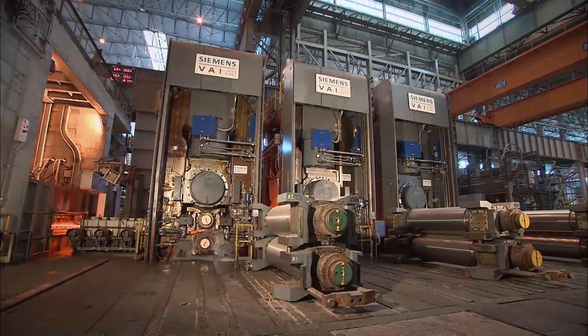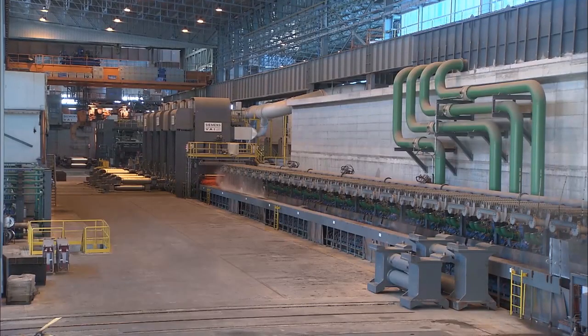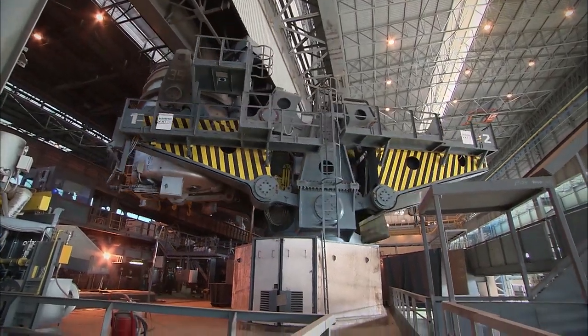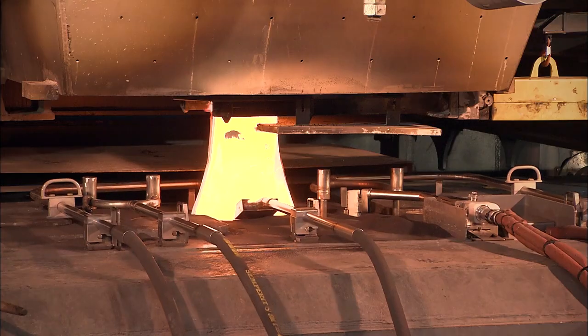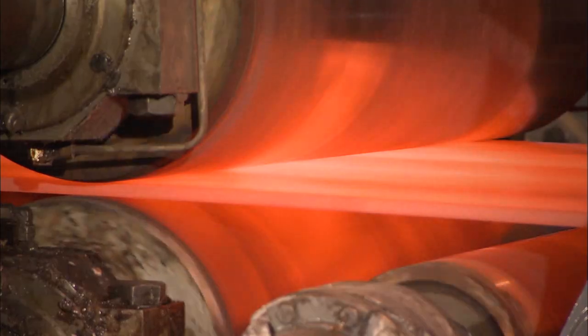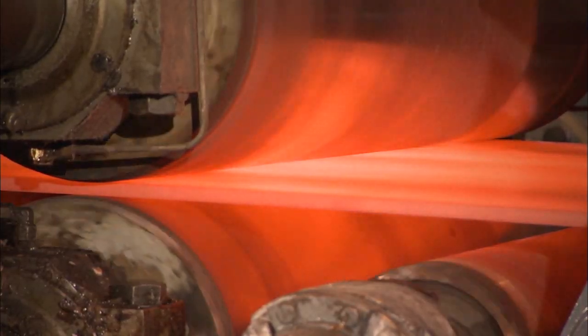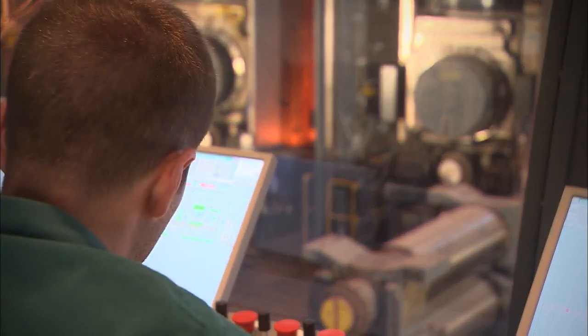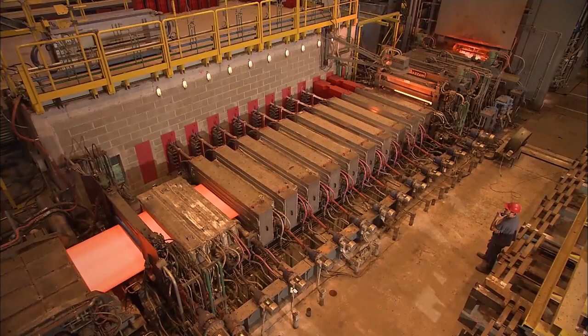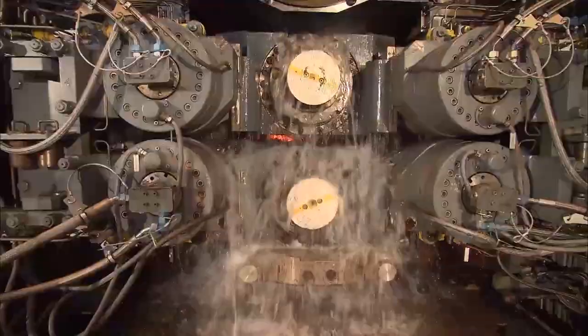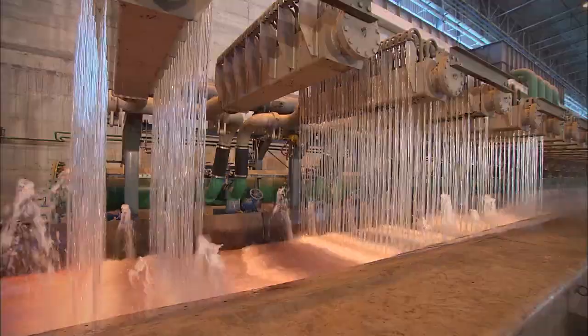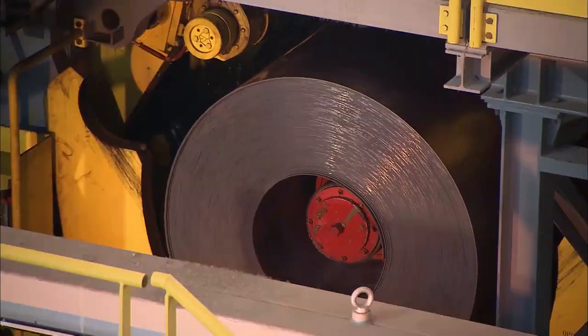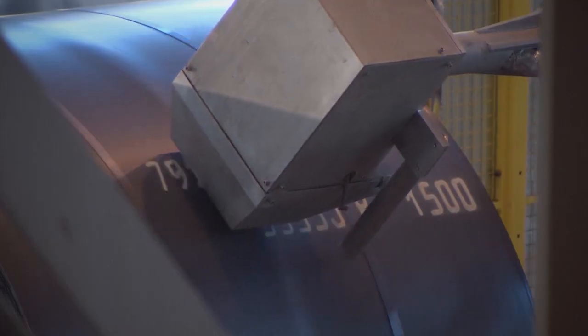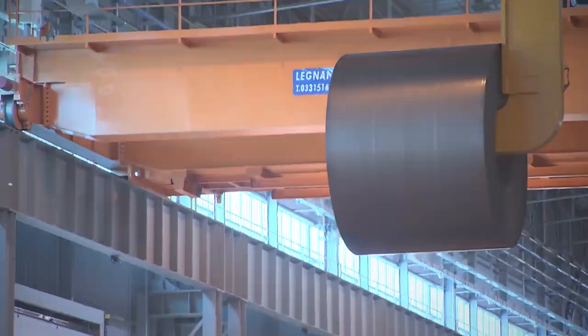Here, the process is extremely compact, and due to a powerful caster, the first rolling stage can follow immediately. The soft core allows perfect shaping during the initial rolling phase with respect to both crown and wedge. Subsequently, the thin intermediate strip can be reheated in just 10 seconds before entering the second rolling phase, thus offering a perfect split between recrystallization in the high reduction mill area and thermomechanical rolling in the finishing area.